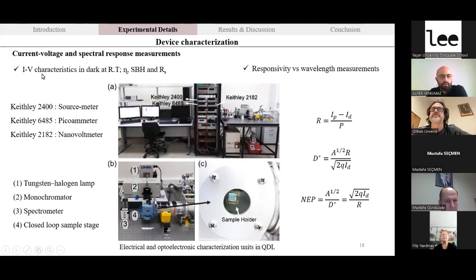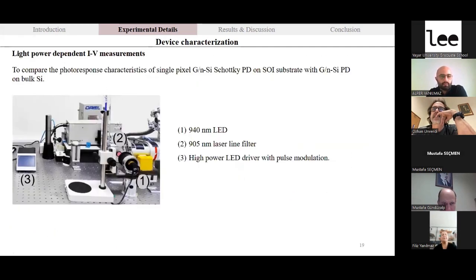Here we use the current versus voltage characteristics of the devices in a dark environment at room temperature to get the ideality factor, Schottky barrier height, and series resistance of the devices. Responsivity versus wavelength measurements were also done to characterize our detector arrays. Light power dependent current versus voltage measurements were done to compare the photoresponse characteristics of the single pixel graphene n-type silicon Schottky photodetector on silicon-on-insulator substrate with the reference detector.